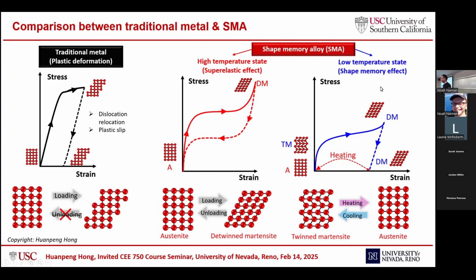And when this material is in the low temperature state, we load it from the martensitic phase to the detwinned martensitic phase. Unloading it is just like normal steel, but if we heat it up, it can completely transform to the austenitic phase. So the heating and cooling is phase transformation, not plastic deformation. That's why this material can memorize its original shape.